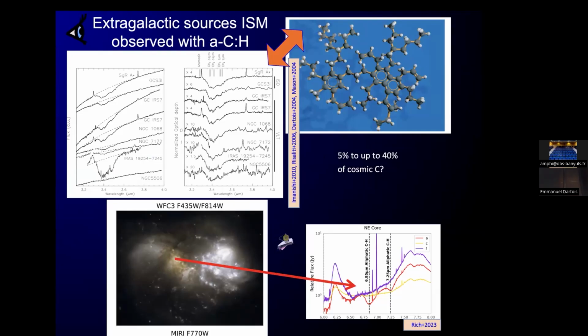But with Spitzer, we had analyzed a lot more, also looking at the mid-infrared absorption, and we found something like 40 or 50 galaxies where you see these features. So looking at the features at 6.8 and 7.2 micron. And these again are some recent observations with James Webb of the presence of these in the diffuse ISM.